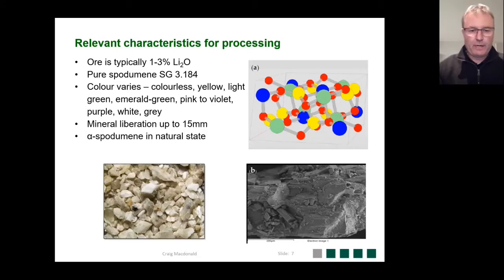For those operating spodumene concentrators, the image in the bottom left is a typical 6% lithia spodumene concentrate, and the top size there would be around about 5 millimeters.